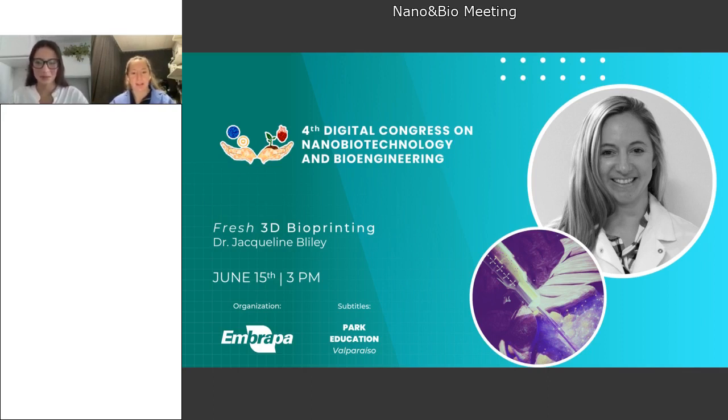So we've actually printed a lot of different hydrogel materials. We have done a lot of work specifically in type 1 collagen, but we have printed mixes of Matrigel, type 3 collagen, as well as alginate, fibrin, PDMS, which is an inert material that's not normally found in the body, but also is helpful to cells. And we've also printed many different cell types. I didn't really go into that. We printed cardiomyocytes or heart muscle cells, as well as endothelial cells. So a lot of different materials.